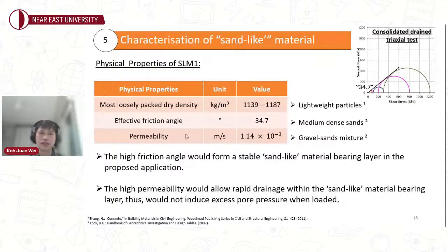And for the effective friction angle, we are using a consolidated drained triaxial cell. The value of the friction angle is about 35 degrees, and is actually comparable to a medium dense sand, which is what we want. And the permeability is in the order of 10 to the power of negative 3 meter per second. It's actually comparable to a gravel sand mixture.